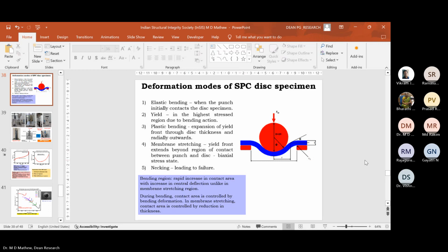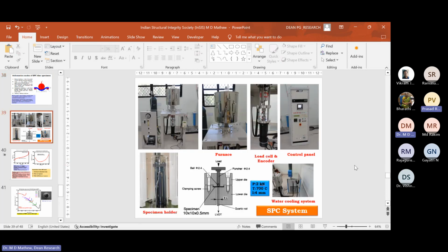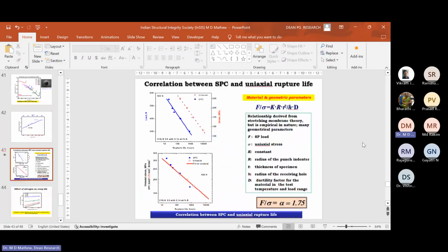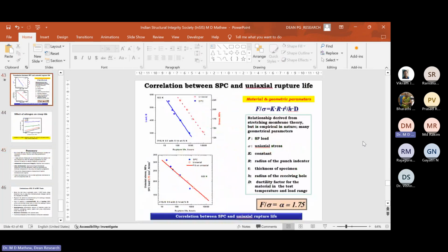In the case of the ball indentation test, both alpha and beta are roughly the same for all kinds of materials, so there you have no issue. For an unknown material, you can use the same numbers, because for a lot of materials it has been shown that the number is the same. In the case of small punch creep, again, you have a value which is roughly 1.75. That is the ratio of the load to the uniaxial stress. But you will have to do at least a few experiments and generate this number, and then of course you can use it.